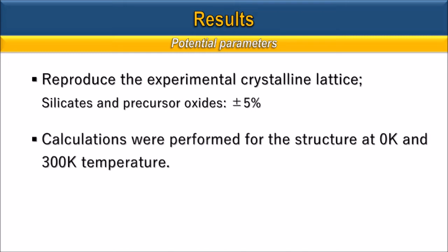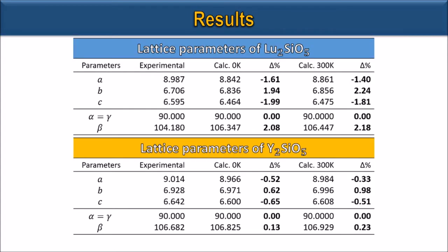Another important piece of information is that in all calculations in this work, we simulate the structures at 0 and 300 Kelvin of temperature. These two tables show that the potential parameters were able to reproduce both structures with differences between experimental and simulated parameters below 3%. The difference of all lattice parameters for yttrium silicates is below 0.98% at both temperatures. That shows that the potential sets very successfully describe these materials. For the lutetium silicate structures, this agreement is less accurate, below 2.24% for room temperature, but still within acceptable values.